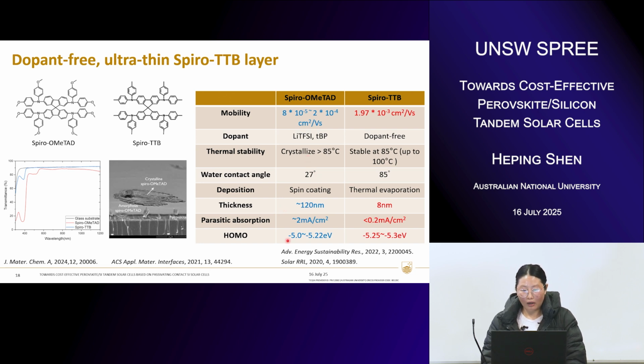Also, they are usually very thick. 100 or 120 nanometers is the minimum we can have through the solution method. That causes a significant loss of current because of absorption loss, up to 2 to 3 milliamps. And of course, the energy level we found is also not ideal, particularly for the wide bandgap perovskite solar cell we are developing. On the other hand, we explored different materials and identified spiro-TTB as a potential candidate to replace this material.